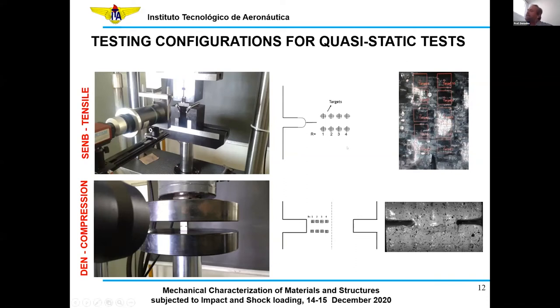And by measuring the strain here, and also using the Westergaard expression for the crack tip stress field, we can actually measure directly the stress intensity factor, skipping all the standards that we have available right now for metallics, but not for composites, right? We have done that for the SENB specimens and also for the double edge specimens, as you can see here. Here we have some details of the failure within the notch in compression, which is a failure dominated by fiber kinking, a desirable failure mode that we excited in this test.